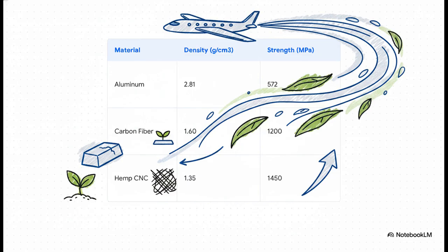Look at the heavy density of aviation aluminum. We're at 2.81 grams per cubic centimeter, but with a tensile strength of just 572 megapascals. Carbon fiber definitely improves on that. It drops to a 1.60 density while hitting 1200 megapascals of strength.